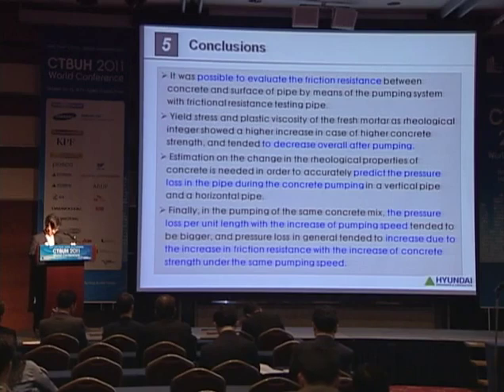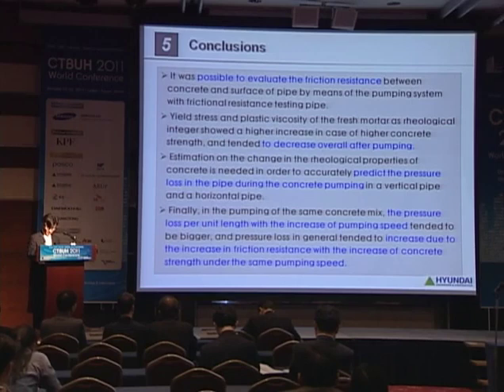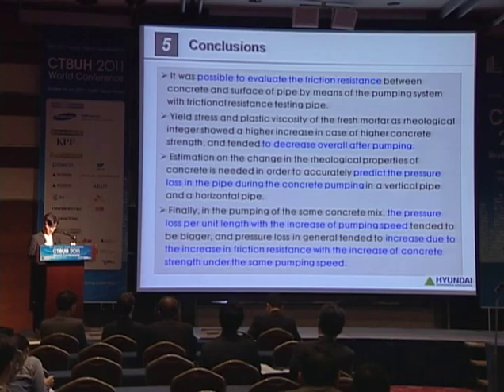Finally, in the pumping of the same concrete mix, the pressure loss tended to be bigger with the increase of pumping speed, and pressure loss in general tended to increase due to the increase in friction resistance with the increase of concrete strength under the same pumping speed.